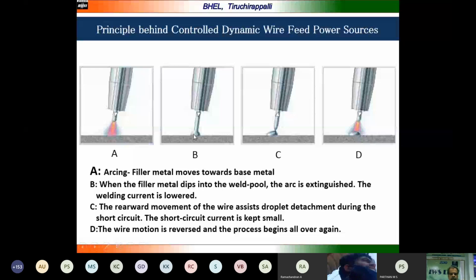Again, due to the rearward movement of the wire, it assists droplet detachment by moving the wire in reverse here, and then the short circuit current is kept very small at this time. Again, the wire motion is reversed and the process begins all over again. That is why, by minimizing the current at this point and this point, the heat input is lowered and the welding can be done very easily. Even copper to steel can be welded successfully by using this process.